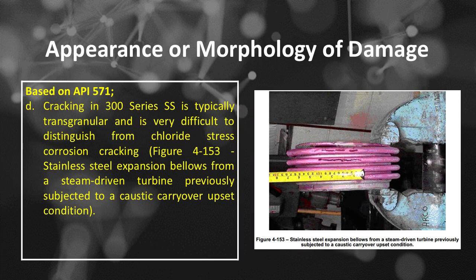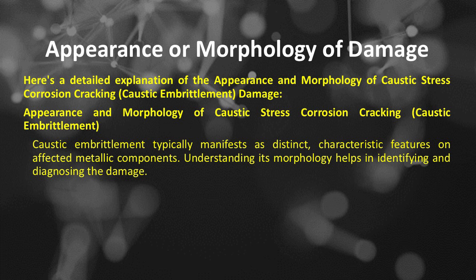Number D. Cracking in 300 series SS is typically transgranular and is very difficult to distinguish from chloride stress corrosion cracking. See Figure 4-153: stainless steel expansion bellows from a steam-driven turbine previously subjected to a caustic carryover upset condition. Here's a detailed explanation of the appearance and morphology of caustic stress corrosion cracking.